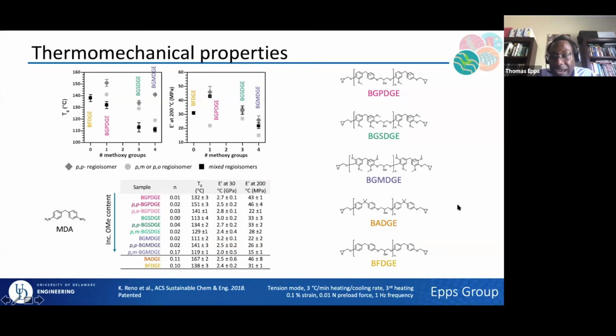We can actually take BADGE, which is that commercial bisphenol-based material, the epoxy version, so basically a diepoxy, cure it with an MDA, and, for example, make a nice epoxy resin. We can do the same with these top three, which are bio-based materials. This one down here is the commercial analog to BPA, except you can see that it's missing the two methyl groups on that bridge. But the key point is basically shown over here.